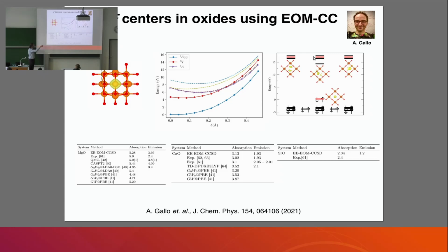And it's quite nice, actually, to then also compare them to the experimental results, but also different post-DFT approaches, in particular the GW plus BSE approach. And we can see that for all of these systems, we get a pretty good agreement for the absorption energy, and also for the emission energy with the experiment, except for magnesium oxide.